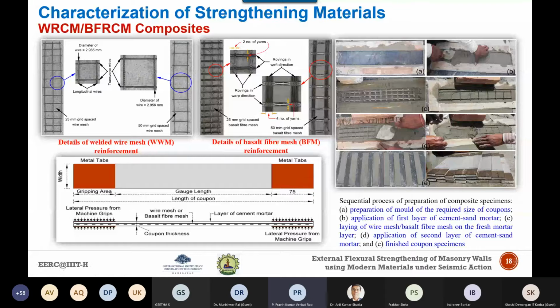Now, what we do is, we first provide a layer of plaster of maybe 5 to 6 mm, and then we provide this reinforcement as a sandwich material. That's why it is called a composite matrix, or also coupon specimens. So here we have provided the wire mesh as well as the fiber mesh, and then again a second layer of plaster. Then the specimen has been cured for 28 days, and after curing, they have been provided with these metal tabs.